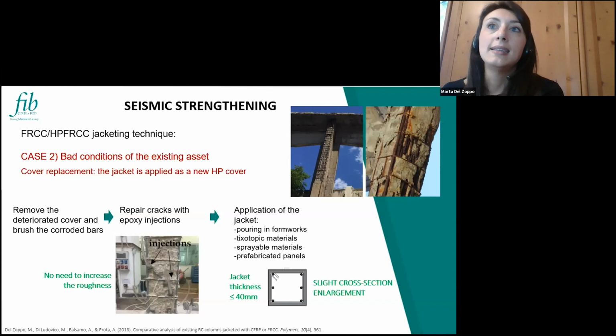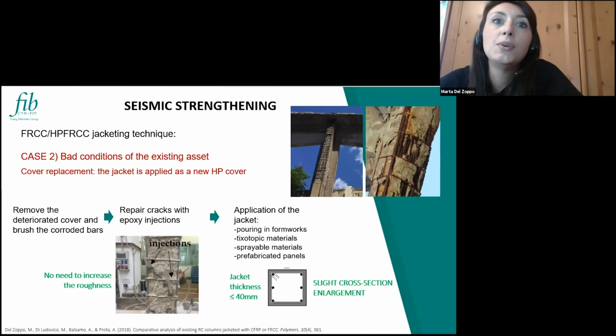So the first step is, in this case, to remove completely the cover and of course clean the bars if we have corrosion. Then we need to repair the member if needed. If there are cracks, we need to do some epoxy resin injection. But of course, we don't need to increase the roughness, because thanks to the removal of the concrete cover, the surface will be rough enough to ensure a good bond between the jacket and the original member. And then we can apply the new concrete cover. In this case, the cross-section enlargement is really null or negligible, because the jacket will replace completely the original cover.